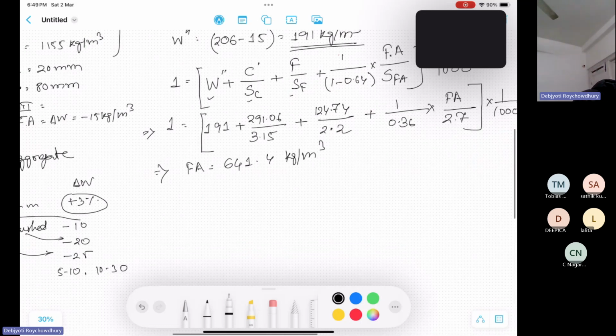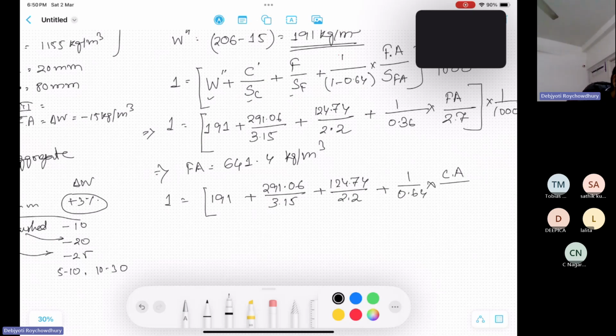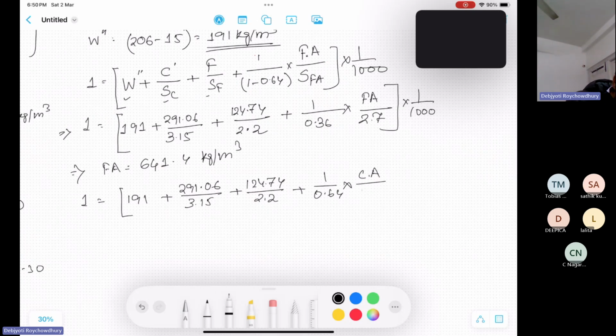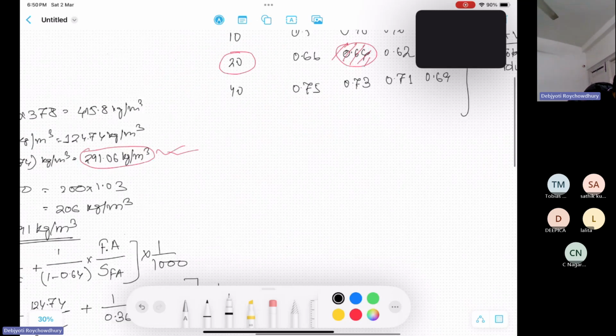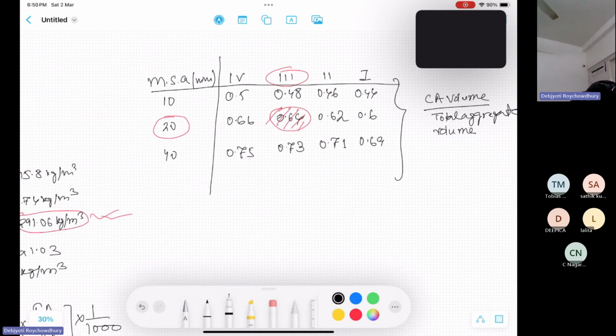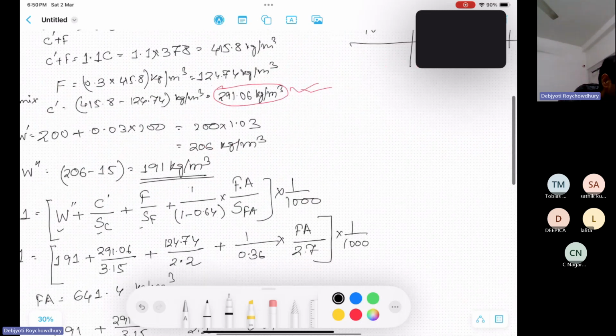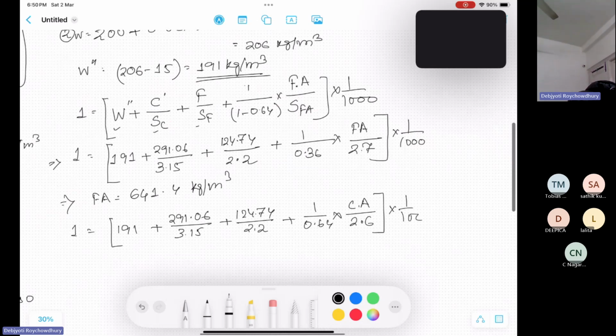And if I want to calculate the coarse aggregate content, the same formula is there: 191 plus 291.06 by 3.15 plus 124.74 by 2.2, by 0.64, times coarse aggregate. The specific gravity of coarse aggregate is 2.6. The table is only for the coarse aggregate, not the fine aggregate. So it is the volume fraction, volume of the coarse aggregate by total aggregate volume. Similarly, we get the coarse aggregate content as 1098.07 kg per meter cube.